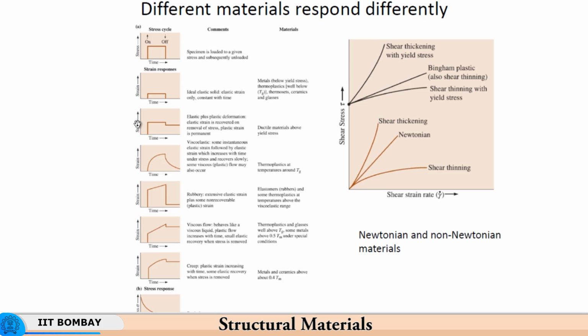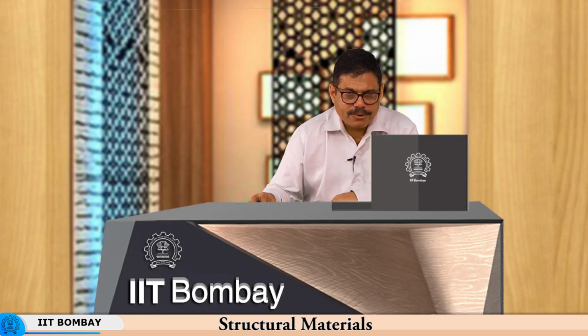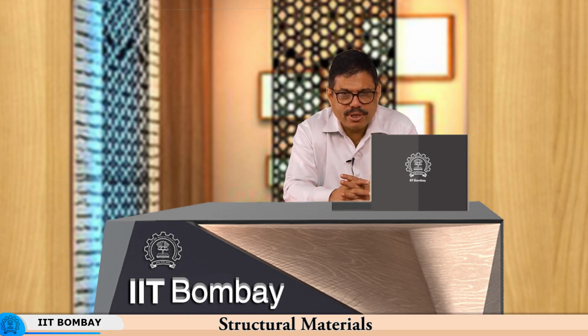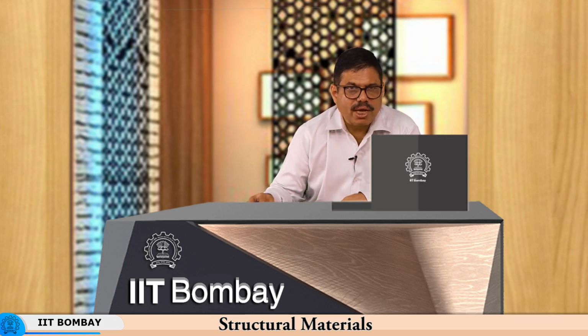Now, different materials give different responses. You have an ideal elastic solid over here where the elastic strain, or fully recoverable strain, is shown over here. So, at the end of the cycle, if we call this a cycle, the strain is 0, the strain that is retained by the material is 0. These are typically materials which are of course metals, but then there are metals below yield stress. Then you have thermoplastics which are well below glass transition temperature, because thermoplastics are essentially chains of hydrocarbons, and so these chains get extended and they come back to their original position, and this happens provided the temperature is below the glass transition temperature.